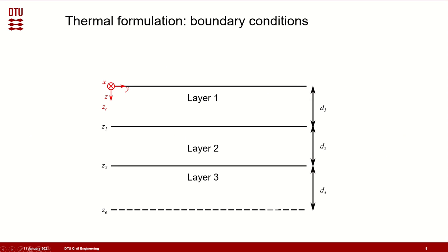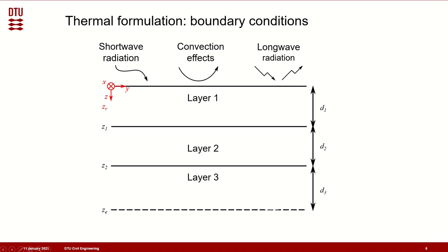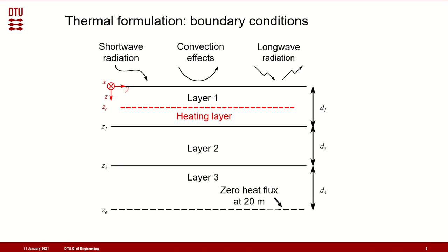Here represented is the model three-layered half space. The top layer, layer 1, represents an asphalt concrete layer. The middle layer, layer 2, represents an unbound granular base, and the bottom layer, layer 3, represents the subgrade and deeper soil mass. The upper boundary consists of an energy balance at the surface, controlled by weather effects. In this work, the shortwave radiation, convection effects originating from the airspeed and the air temperature, as well as the long-wave radiation are considered. A zero heat flux serves as a lower boundary at a depth of 20 meters. The heat source is placed at the depth z_R.